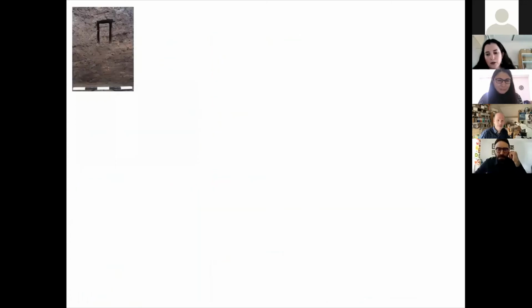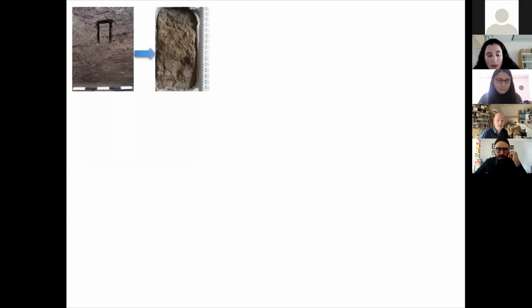So I also think when it comes to sampling, it's useful to bear in mind the process that the samples undergo once they're in the lab. So in my particular case, I tend to open the samples once I'm in the lab so that they have a surface to begin to dry out. And I conduct subsampling of the layers that I see after cleaning the block for other techniques such as phytolith analysis and geochemical analysis. So I think something between 1 and 4 grams should be enough.